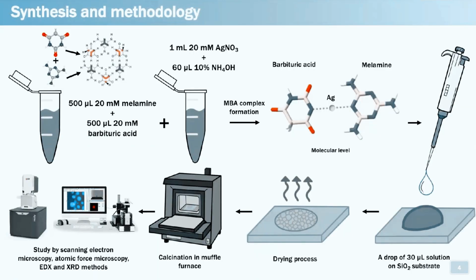In the first steps, melamine and barbituric acid were mixed together to form small crystals of MBA. After that, 10% ammonia solution and silver nitrate were added and the crystals dissolved. An organometallic complex was formed, applied on quartz glass, dried, thermally treated, and after that studied by various methods.